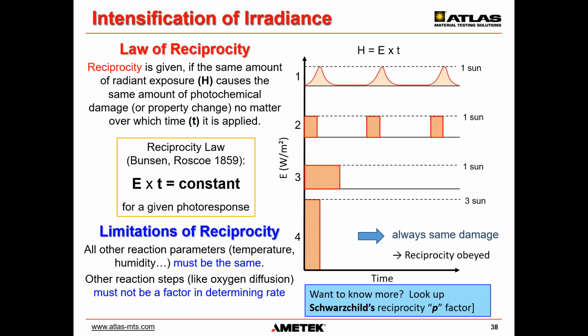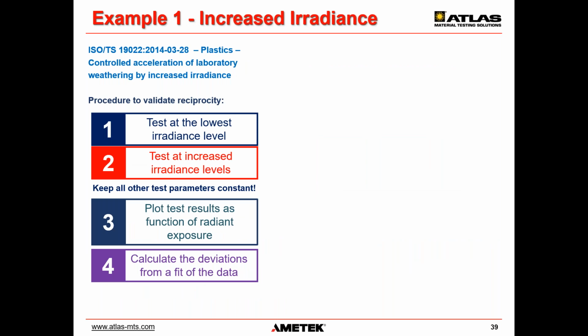Moisture control can become difficult, especially at high irradiance levels, which can affect specimen temperature, moisture absorption, and desorption rate. Also, oxygen diffusion and availability in the sample matrix is a key factor in determining polymer degradation, and this cannot be accelerated adequately. And there are some dark time reactions for certain polymers that can't be photoaccelerated. These are only some of the reasons why reciprocity mostly doesn't hold true. But there is a technical way to find out if it works or not.